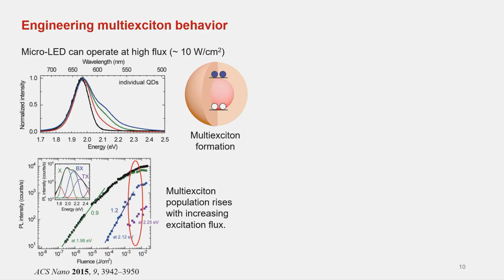There is good literature doing a lot of relevant studies, and based on their measurements, 10 watts per centimeter squared lies around in this range, and you can see the biexciton intensity is almost at the same scale compared to the single exciton. So this is something that we need to care about when engineering the quantum dots.